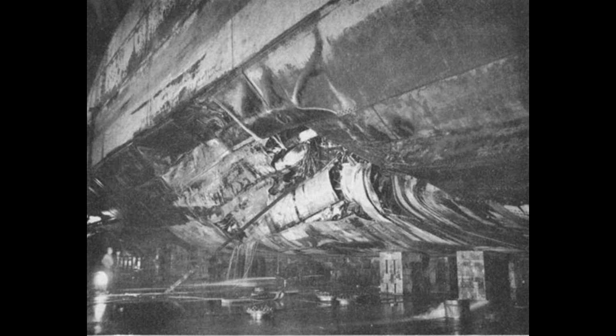When inspectors examined LST-338's hull, they found the explanation for her survival. The explosion had initiated microfractures in dozens of welds throughout the bow section, but none of these cracks had propagated beyond a few inches. The stress relief procedures, the careful heat treatment, the multi-pass welding technique, all of it had created a structure that could absorb damage without catastrophic failure.